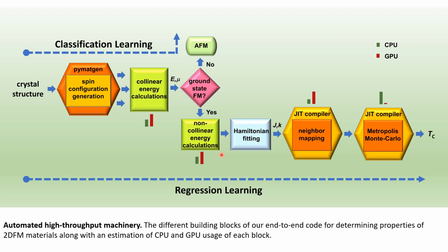So non-collinear energy calculation means that the spins don't have to be either in up or down directions, but you can orient the spins in an arbitrary direction in a 3D sphere if you like. And what we do, we indeed orient the spins in different directions and we calculate the energies from them. From this, what we get is the easy magnetization axis, which is the direction where the energy is lowest when you orient the spins in that specific crystallographic direction. And we also get the amount of anisotropy, which is the amount of difference in energy, the amount of gain in energy or loss in energy when you change the direction of the spins.